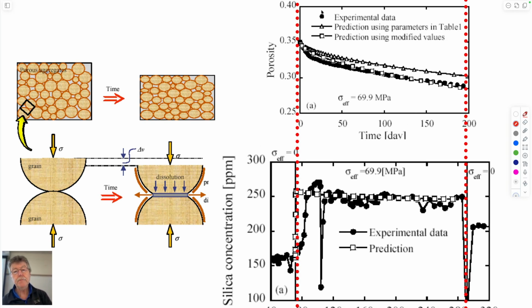This happens to be some data from an experiment that was just a whole bunch of glass beads, quartz, put in a reactor under 70 MPa, and left with water in that reactor for the best part of a year, half a year, to measure the porosity change as the load on that sample is constant, but as it's allowed to compact, as pressure solution allows the grains to grow into each other by this process. So as a function of that, the measured data are these dots here, the model are these symbols which represent these processes just as a very simple model. So you're able to follow exactly what you see here, is that you lose porosity in your bead pack as a function of time. Constant stress, so stress isn't changing. All that's happened is you've jacked up the temperature to allow this process to activate, and it slowly activates.